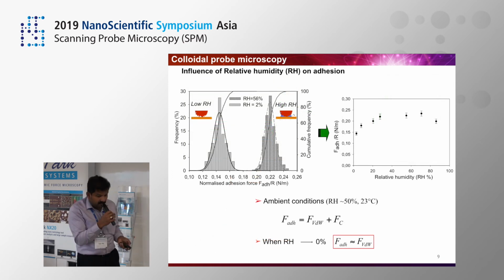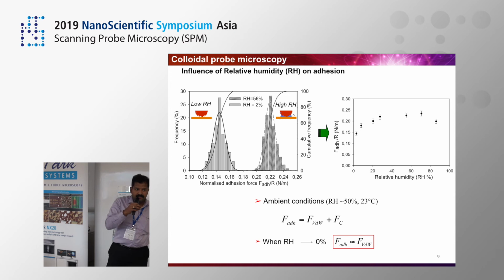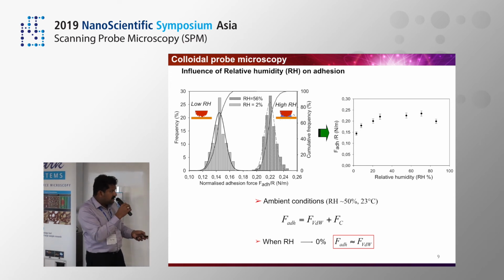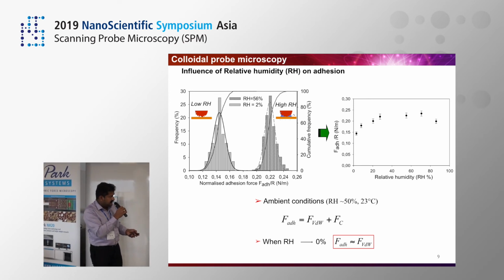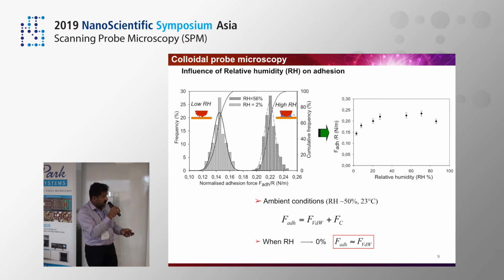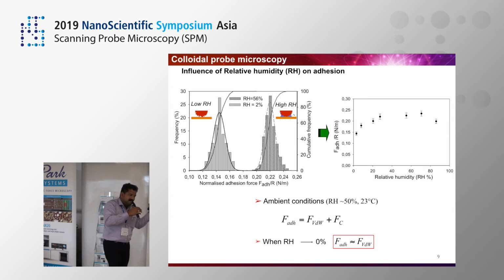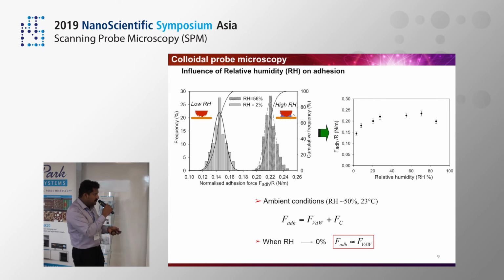Now the adhesion force that we measure is dependent on the relative humidity of the environment. Here we show that when these measurements were performed at low humidity, the adhesion forces were low, indicating that the condensed water molecules from the atmosphere are contributing to the adhesion. Here is the normalized force versus the relative humidity, and we can see that at low humidity, adhesion is low, and with increasing humidity, it is increasing, and it drops a little because at very high humidity, the capillary force actually decreases, because you are essentially under a water layer. So the force that we measure under ambient condition is a sum of van der Waals plus capillary forces. At low relative humidity, the adhesion force is purely from the van der Waals component.